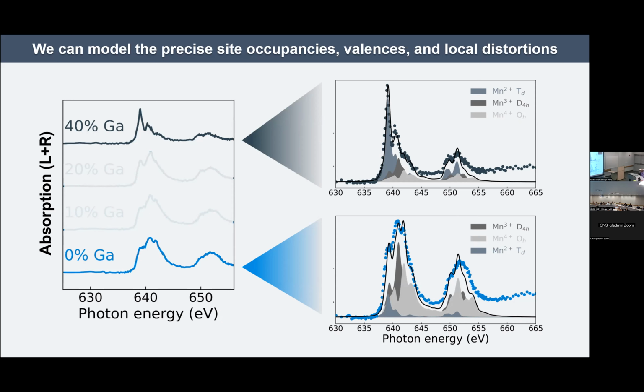And there's one more little Easter egg in this data, which is that not only do we need those 3 different manganese oxidation states sitting on tetrahedral and octahedral sites, but we actually need to build in a Jahn-Teller distortion for our manganese 3+ in order to accurately capture the features of the data. So we can learn an incredible amount about what each of the elements is doing in these materials with this absorption method. And what we see when we go from 0 up to 40, just taking the 2 limiting cases, is that there's an overall redistribution away from 4+ and 3+ towards 2+, which makes sense because we know that gallium has a stable 3+ oxidation state. And so something else has to adjust to let gallium maintain its 3+ oxidation state.